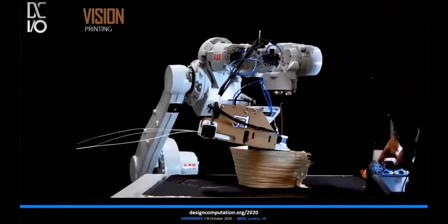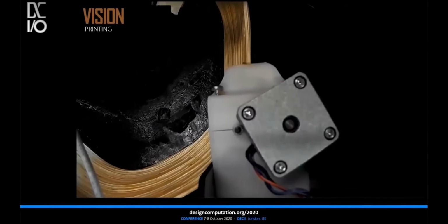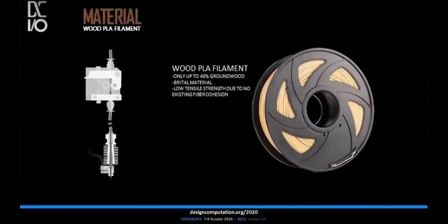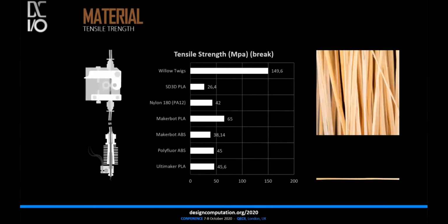Current methods of 3D printing with wood as compound material, for example, used in FDM or fused deposition modeling printers, can imitate up to a certain extent the visual appearance of wood and are open to the consumer market. However, this compound material only has a small proportion, up to 40% of groundwood. While the percentage of this wooden content may increase in the future, this only imitates the overall look and color scheme of wood and does not take over its mechanical characteristics, like its tensile strength and anisotropy, due to the lack of long fibers. In comparison, the treated willow twigs create a combined filament with a greater tensile strength of real solid willow. This makes wood the largest proportion of this extrusion.